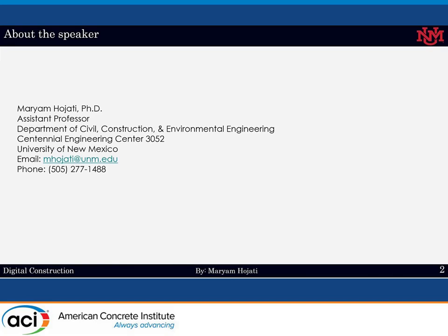So we did the freeze and thaw test. ASTM designed some requirements for the freeze and thaw test to make sure that if we pass those requirements, it means the material performed well. Our material passed all of those tests. It was working well under freeze and thaw conditions. We didn't do any shrinkage test.